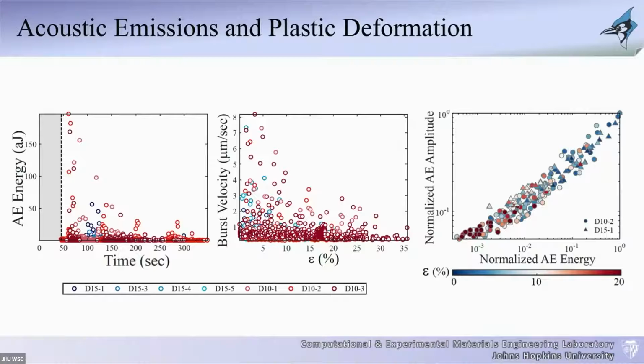So the big events, those that are associated with large amplitudes or large energies, these are the big earthquakes that are happening in the material. They typically happen predominantly at small strains. When you go to large strains, the amount of earthquakes and the earthquakes that you have are much smaller. We think this is related to the types of defects that are forming internally that are blocking the earthquakes from having a significant amount of energy or a significant amount of amplitude. So it allows us now to actually visualize the events themselves with a higher fidelity than the load displacement calculations.